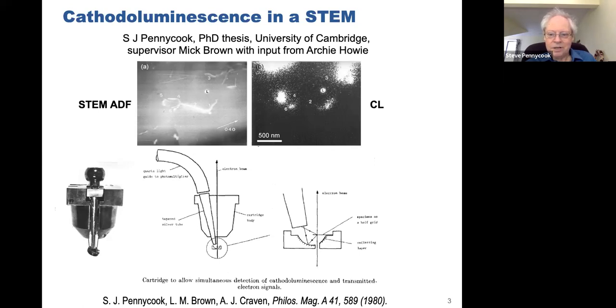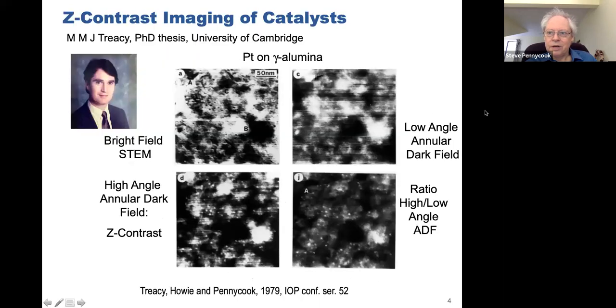But how did the Zed contrast come around? This was with my student, M M J Treacy, who was doing his thesis at the same time, and his supervisor was Archie Howie. And he was having trouble seeing these tiny catalyst particles in bright field because of diffraction contrast, especially on gamma alumina crystalline supports. And so he had this idea, why not go to high angles, when that diffraction contrast should be replaced by thermal diffuse scattering. So I built a little detector to replace my mirror. And this was the first high angle annular dark field, one of the first images ever achieved. And you can see it does nicely show the contrast from the particles.